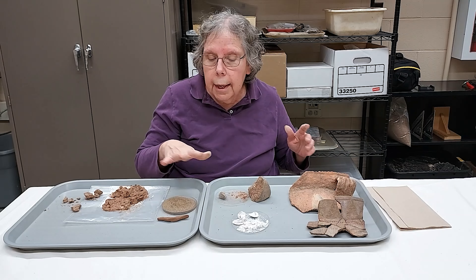Let's say you find something that you think might be pottery. Here are some things to look at. First, look to see if it has two relatively parallel sides — the inside and the outside of the vessel — and does it have a slight curvature? Quite often pottery will if it's coming from a relatively small vessel. So you have something relatively thin and flat with two parallel surfaces. You want to start looking at the cross section. If you can't break it, it's a stone — pottery usually breaks pretty easily.